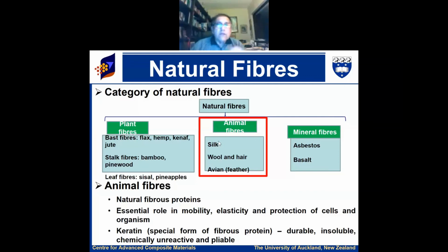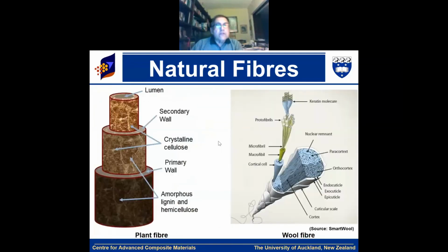But we also wanted to have a look at silk and wool here, because New Zealand produces a lot of wool, and they wanted us to look at the wool situation for composite materials from a fire side as well. If you look at the two natural fibers, plant fiber has got lumen and then secondary wall, crystalline cellulose, primary wall, and amorphous lignin and hemicellulose outside. It is almost protecting the inside crystalline cellulosic fibers.